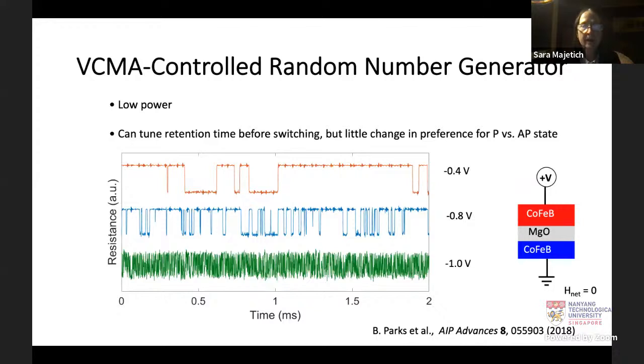However, you do not get the sigmoid curve that you need for some of the other applications. You can see that in the top trace, it's not 50-50, but it's not far from it. In the bottom trace, it's roughly 50-50. So you're not going from 0% to 100%.